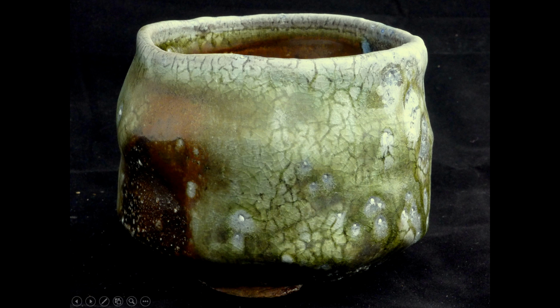Less is more. Initially, when I started working with this, everybody does this to emulate a clay body out of Japan called Shigaraki clay. And it has feldspathic rock and quartz rock in it, little small pieces of it. And so everybody tries to simulate that, which is great, but at the same time, it doesn't occur in nature in tremendous quantities. It's more subtle, like this piece is a beautiful example. And you can see around each one of these little stones, the stone itself is fluxing, it's melting out because it's feldspar, and that's a melter at these temperatures, and so it's basically decomposed granite, and so it forms a little ring of clear glaze around each one of these little spots. Beautiful piece, I think.